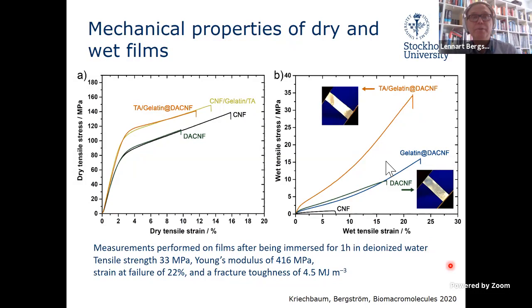The mechanical properties of these materials then: so here on the left, we have the dry tensile strength. I think most of you know that pure CNF films have pretty good dry mechanical properties, with a tensile stress, in this case, above 100 megapascals, and a strain at failure around 16%.